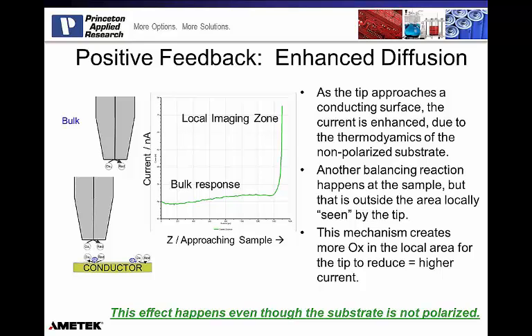And so we can see this in the response. Again, I've got current on the y-axis, and I've got approaching sample from left to right on the z-axis, on the x-axis of the graph. I'm going to have about the same bulk response happening on the current, but then when I get very close to the sample surface, this localized response is seen in the opposite direction. So it's a similar shape, but instead of reducing the current, the current actually increases. And from a fundamental electrochemical point of view, I find that very interesting because this happens even though the conductor is not polarized at all.